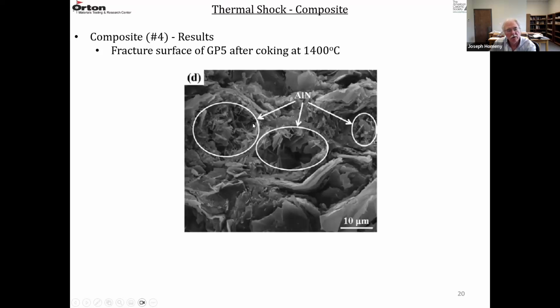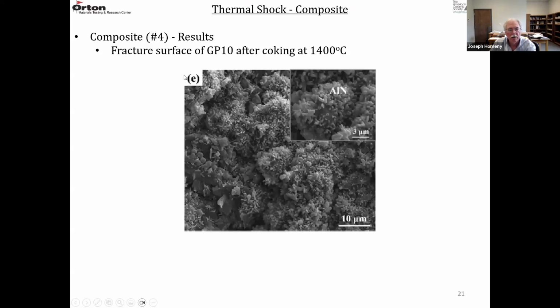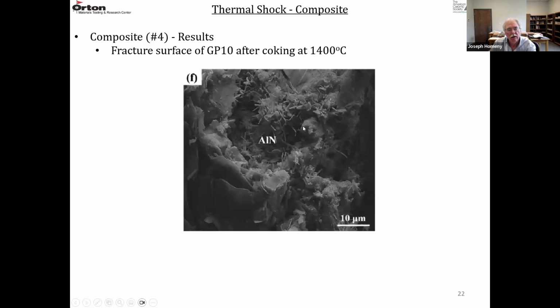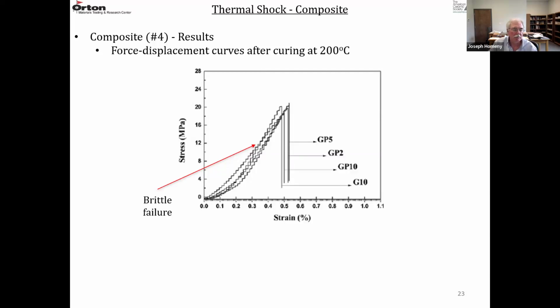And then they're showing where these aluminum nitride crystals are on this one. This is GP5 after 1,400. And you can see some of them are flake-like, some of them are needle-shaped. So these are aluminum nitride crystals. And then this one, GP10, after 1400, you can see a lot of these aluminum nitride crystals forming, like whiskers or needle shapes. And then maybe this is the last one on the fracture surfaces, but this is GP10, 1400 degrees C, and you can clearly see aluminum nitride forming. So the spinel and the aluminum nitride are minor phases.